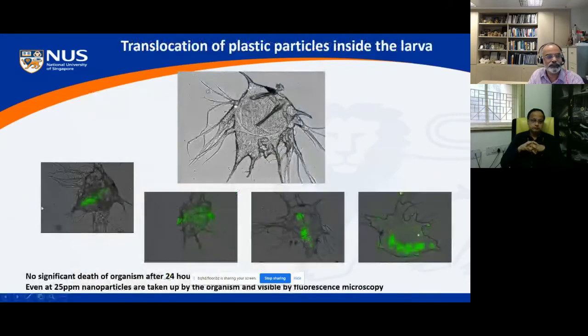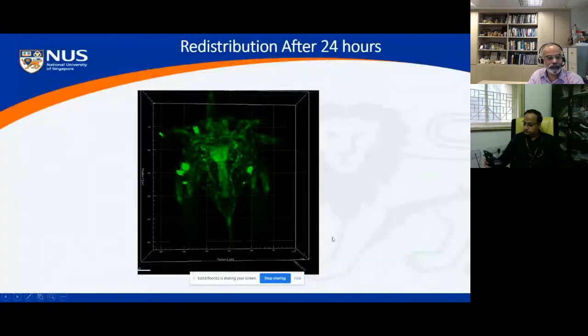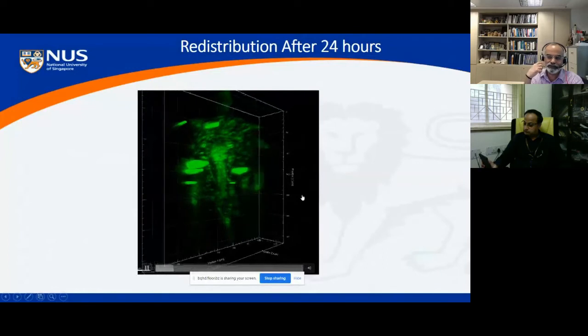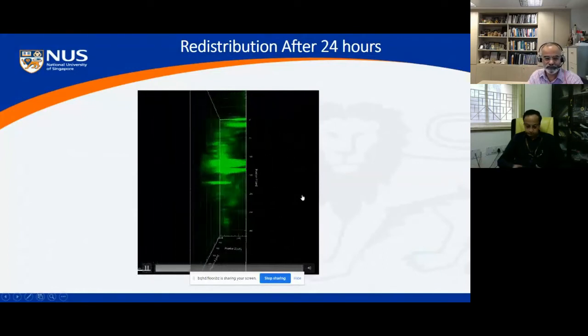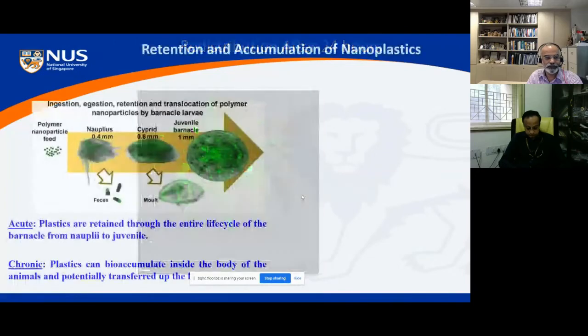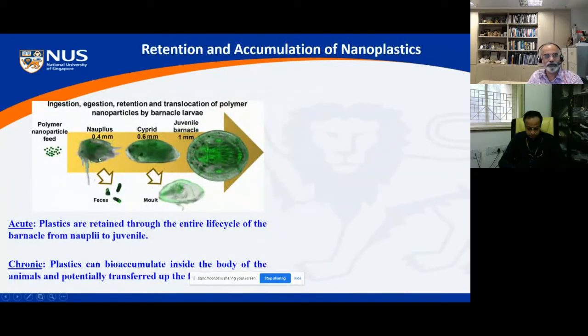They can take it up, and then they tend to disperse all over their body as time goes by. So you can see a nauplius lighted up. I think I have an image here. You can see a clean nauplius here, and then after exposure, you can see the particles tend to disperse everywhere inside the larvae. And we can actually do 3D imaging of the larvae to see where the particles are, et cetera. These results are published in a recent paper. It goes from nauplius larvae all the way to cyprid, which is a juvenile animal, where they start settling down onto a rock or a substrate. And some of the particles do get ejected either through the feces or by the molt.